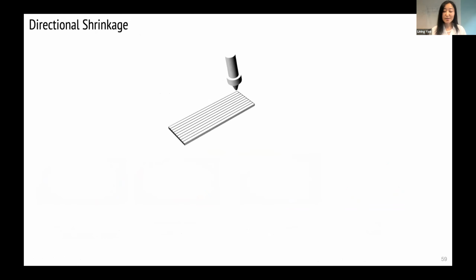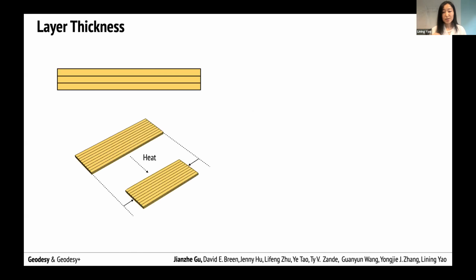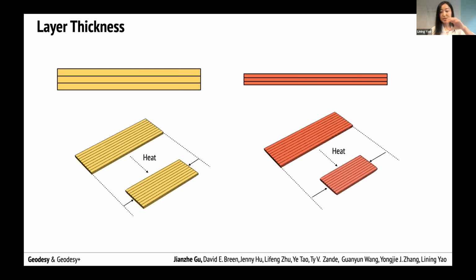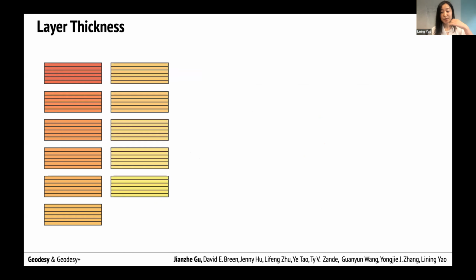So one thing we realized, this was actually led by Jianzhe, a PhD student in our lab, is that each individual layer thickness is a very effective parameter to tune the local shrinkage rate. So that means, again, for each individual layer, not the total thickness of your final artifact, if you print each individual layer thicker, you end up with a smaller shrinkage ratio. And if you print it thinner, you end up with a much bigger shrinkage ratio.